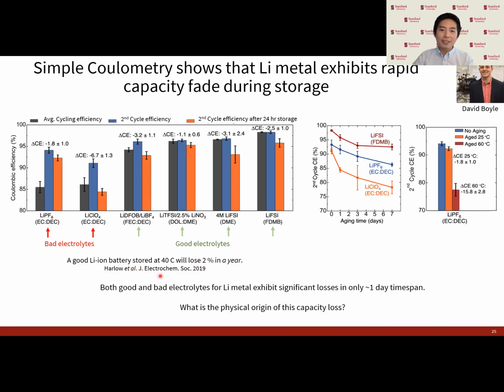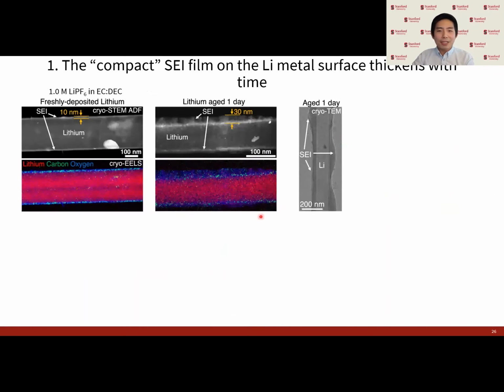So the question now is, what is the origin of this loss and why does it happen? So again, we can turn to cryo-TEM and start to look at the lithium metal SEI before and after this 24 hours of storage. And what we see is that this thin, about 10 nanometer thick compact SEI on lithium metal further grows into thicknesses in excess of 30 nanometers. And this thickening is sometimes very highly non-uniform as well.